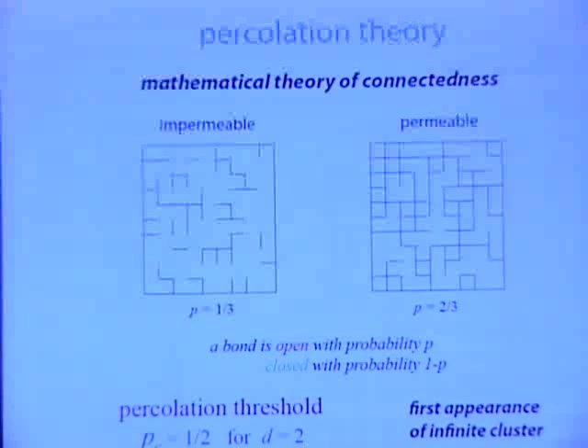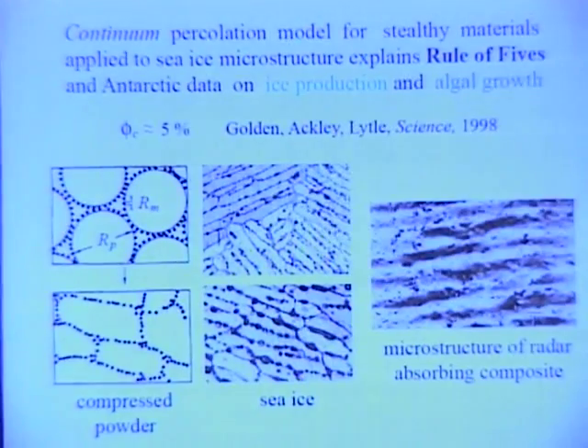For this 2D square lattice, the percolation threshold is rigorously known to be 1/2, or 50%, which is where you have the first appearance of an infinite cluster in an infinite version of this. Now, the first question is, why is what we think would be the percolation threshold 5% in sea ice, which is very different from the classic lattice models? My first observation in this area was simply that the microstructure of sea ice was very similar to so-called compressed powders, which were used in the development of stealthy or radar-absorbing composite materials, where they randomly mixed carbon black or silver particles into a polymer host to achieve conductivity and the desired radar-absorbing characteristics.